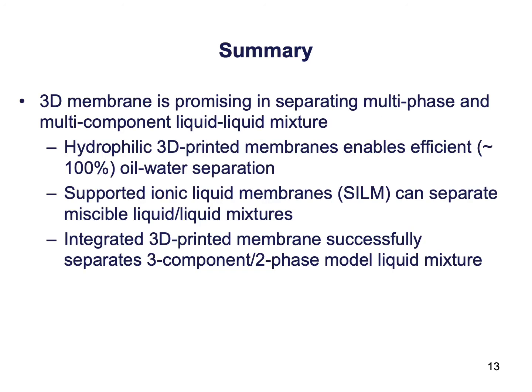In summary, we have demonstrated 3D printed membrane is promising in separating multi-phase and multi-component liquid-liquid mixtures. We achieved almost 100% oil-water separation using hydrophilic 3D printed membranes. We showed that the supported liquid membrane can efficiently separate miscible liquid-liquid mixtures. And we successfully performed on-demand separation of a given 3-component, 2-phase model liquid mixture using the integrated 3D printed membrane.